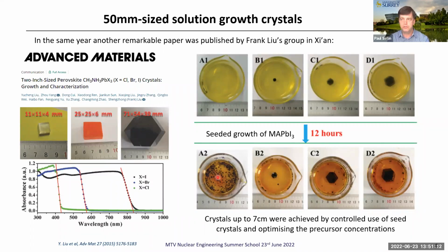The perovskite crystal is very soft, so it's very challenging to polish it. People have developed bespoke polishing regimes designed specifically for soft perovskite material, and it's not at all easy. If you're used to CZT, where you could get your alumina powder out, put it on a lapping machine, put the thing in wax, and off it would go, this is different. So that is tricky.